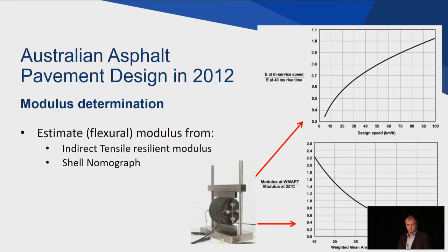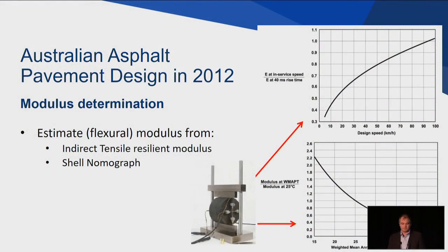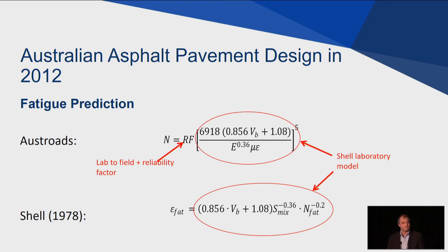One of the issues was that to determine the modulus, they used indirect tensile resilient modulus, and that was done at a single load frequency and a single temperature. And then there were very simple functions to predict the modulus at different design speeds and at different temperatures, and to estimate the flexural modulus. So flexural modulus is what's used in the Shell pavement design method.